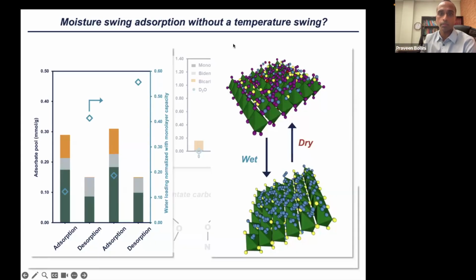So for example, what you see in the data on the left is I'm showing you how many millimoles per gram of adsorbate there is on the surface. And the only variable that I'm going to change is the moisture content. So I'm going to keep this at room temperature and then swing the amount of humidity. So I'm going to go from humid to dry to humid to dry, and you have a swing capacity. Of course, the capacities are not competitive with the temperature, vacuum, or pressure swing processes, but again, the concept works, and there is potential to just do isothermal direct air capture without any swing in either temperature or pressure.